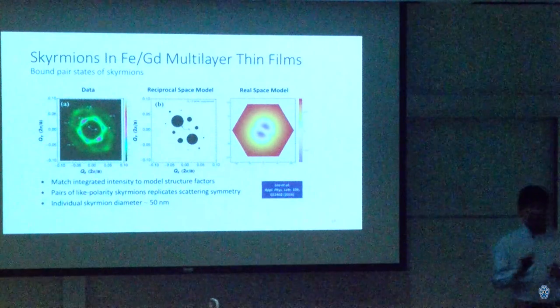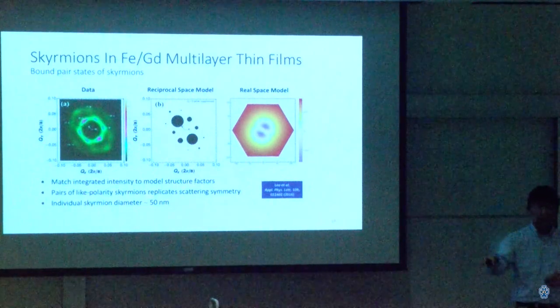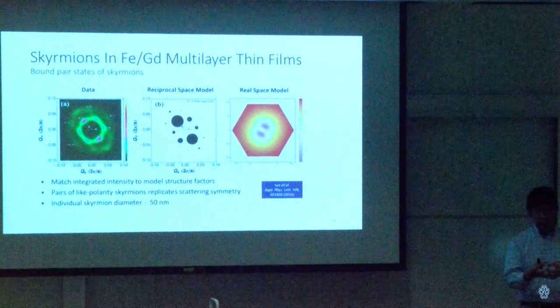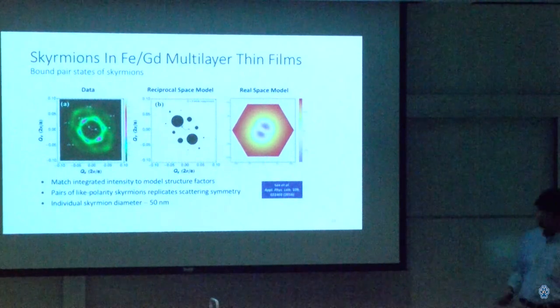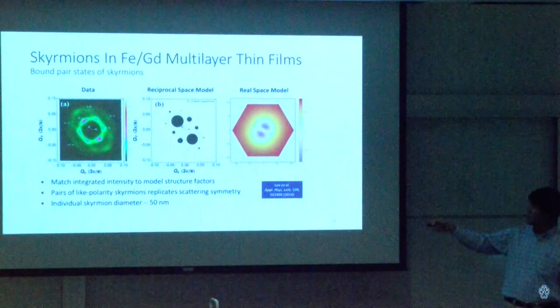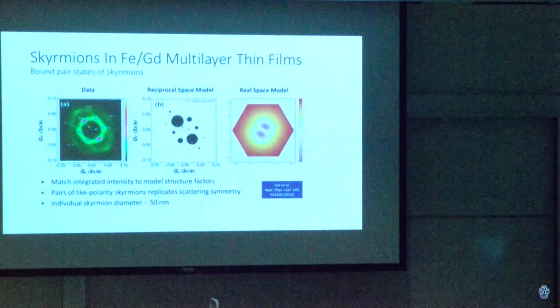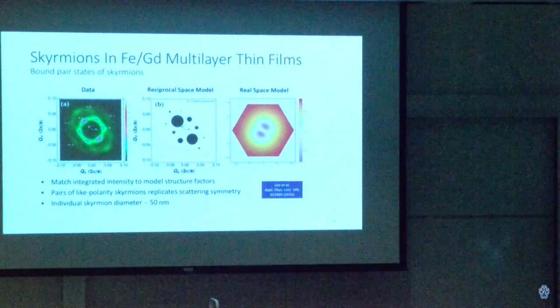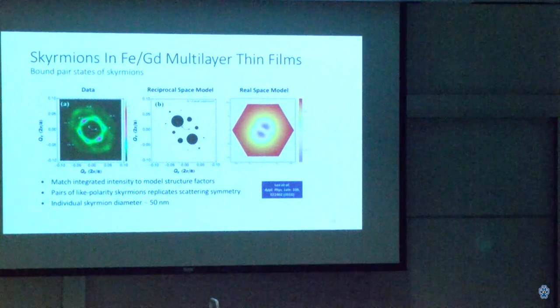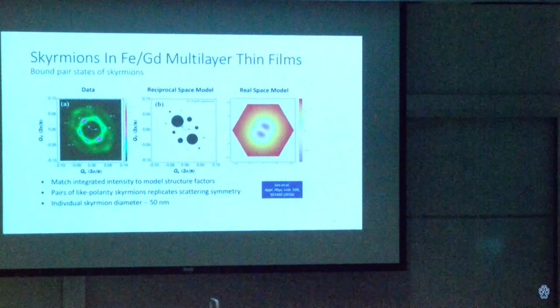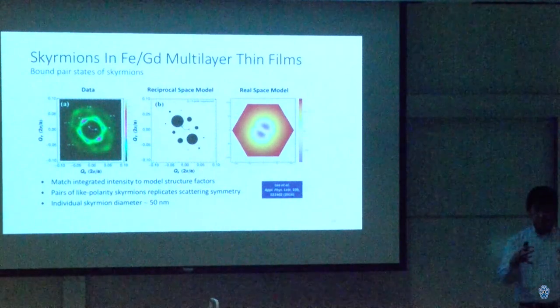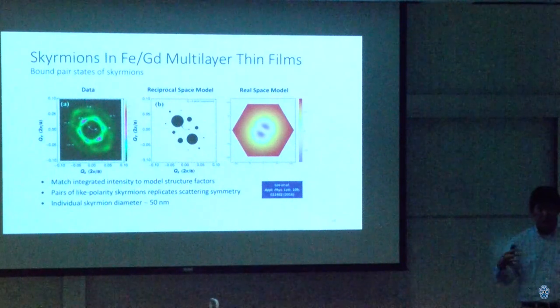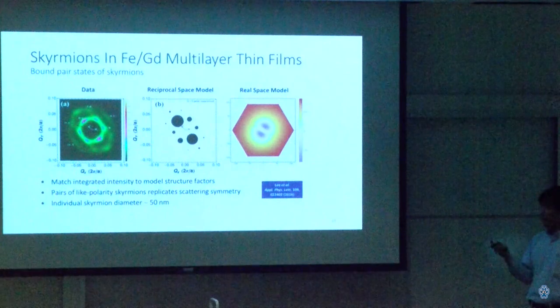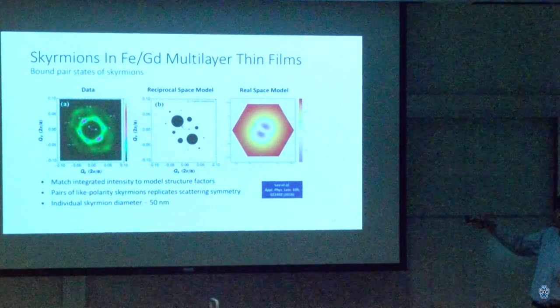We interpret this as meaning that we don't have single skyrmions arranged in a hexagonal lattice, but instead we have two skyrmions with the center here and here arranged in a regular fashion to give us this diffraction pattern. And what that revealed is that even if you have skyrmions appearing in the material, and we did go on later in this paper to demonstrate that these were indeed skyrmions as opposed to some other magnetic entity, what we found is that even though they can form, they don't always necessarily form as individual skyrmion defects. They can sometimes form aggregates, things that can be provocatively described as, say, a hydrogen molecule.